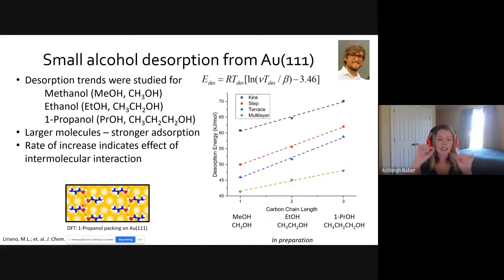But because we can see the difference between molecules adsorbed to terraces and adsorbed to kink sites, we can actually see those molecules that are out there on their own, sitting on a kink site all on their own, and don't have that maximized intermolecular interaction like a molecule would on a terrace. And so what we can see here, I'm showing the slopes of all of these different lines. And you'll see that the slope is larger for the terrace site than it is for the kink site.